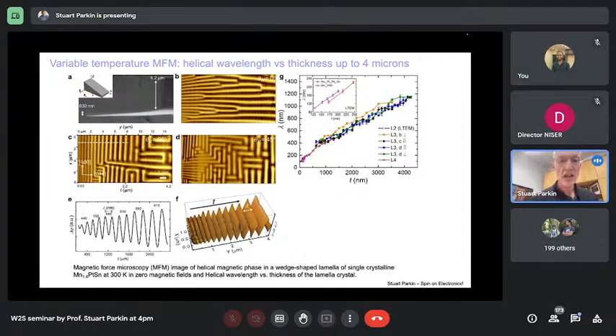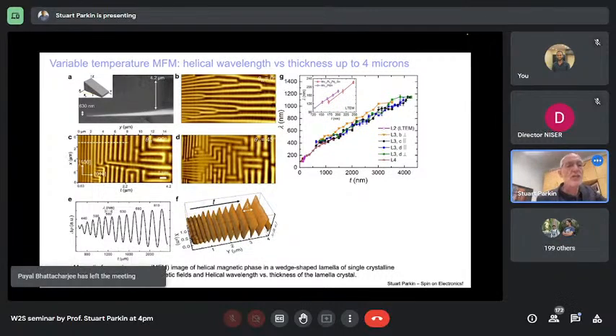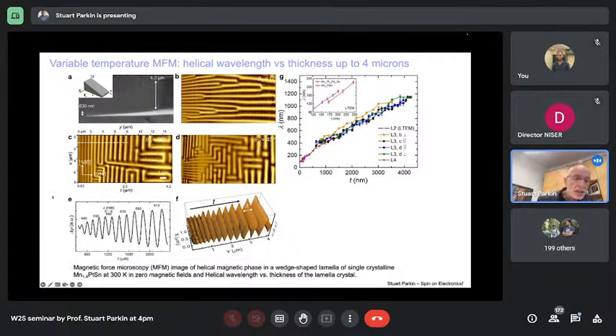But what's most interesting here is a magnetic force microscopy image of a lamella which we've made by focused ion milling, in which the thickness varies, as you can see, from 0.6 microns on the left side to 4.2 microns on the right-hand side. And you can visually see from this magnetic microscopy image that the period of the helix changes from left to right as we increase the thickness. And this is summarized in G. The period of this helix varies from 100 nanometers when the lamella is 600 nanometers thick, to more than 1 micron when the lamella is 4 microns thick.